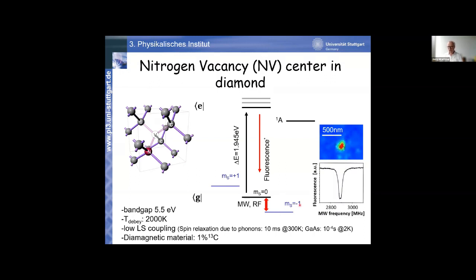And that's what you see here. So if we plot the fluorescence of the system as a function of microwave frequency, here this is on the order of 2.9 gigahertz, for different reasons I'm coming to, then you see that the fluorescence is reduced. So this is just an electron spin resonance experiment with optical detection. And because of the long spin relaxation time, but also because there is very little magnetic noise in the environment and very little phonons being present, it is very easy to do things like driving the system. So looking at the fluorescence intensity as a function, for example, of the interaction time of the microwaves with the spin, you see these type of oscillations, which are just like Rabi oscillations.